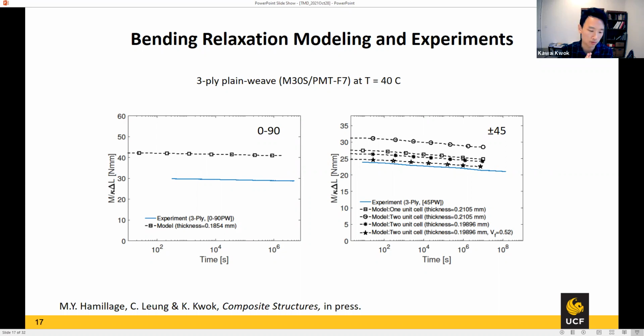So there must be a sort of neutral axis shift in the fiber direction, right? And so the properties are going to be dominated by the fibers. So right now we're trying to incorporate that sort of tension-compression asymmetry to correct that behavior. However, if you look at the time dependence, this is not a bad prediction. The percentage decrease over time is the part coming from the polymer, so that is okay.